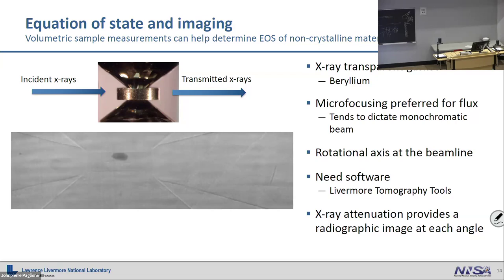So most of these beryllium gaskets get pre-machined. Instead of taking a foil and pressing it down all the way, you start it off slower by machining it into some sort of shape. Normally in ours they have a conical shape inside of them so that they'll sit there and we can indent them. But we don't ask the same of a stainless steel gasket, where we just put a foil in there and press it, because it has, you know, 80% ductility or something like that.